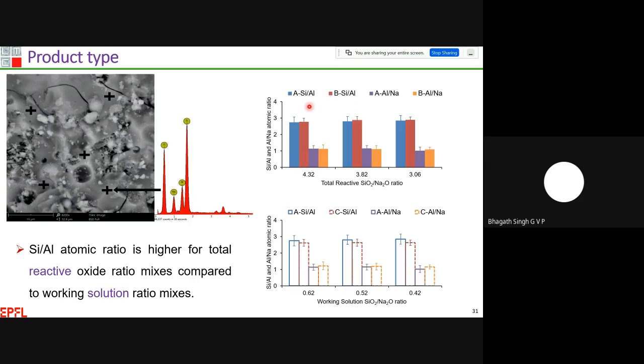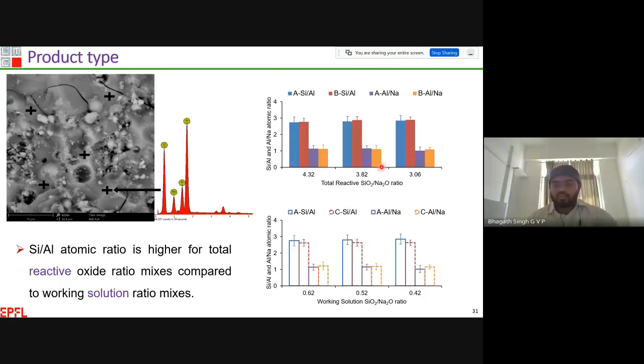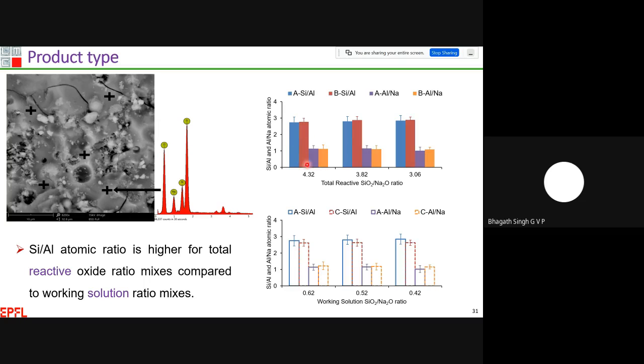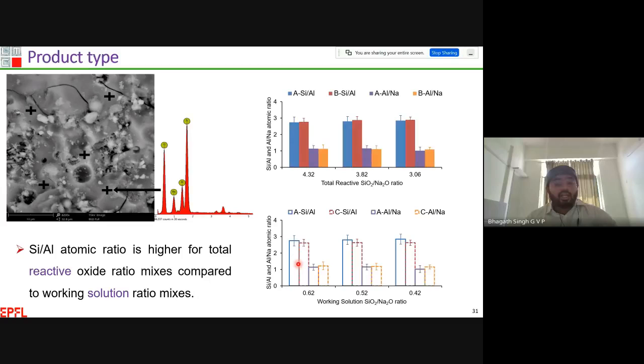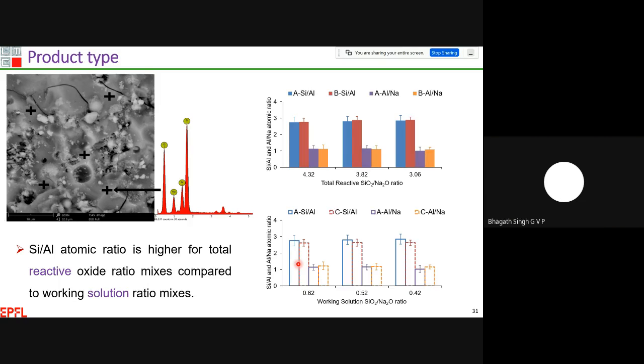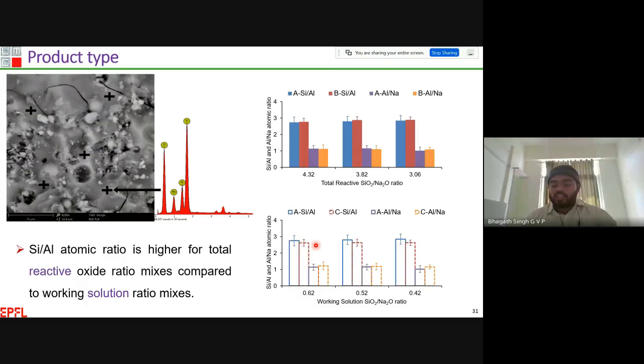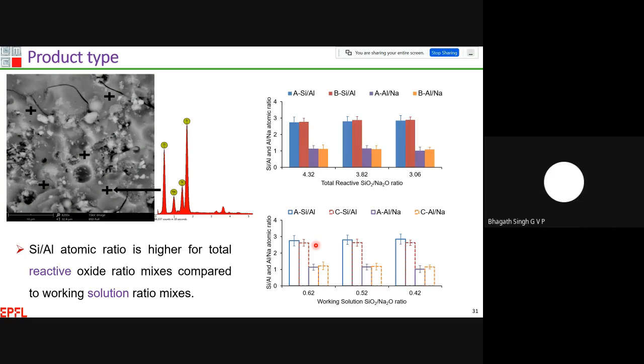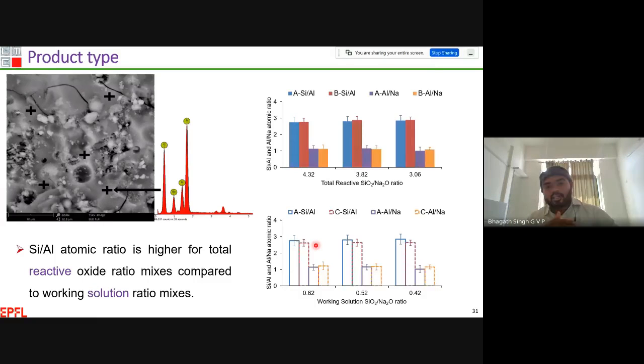Here I have determined the silica to alumina as well as alumina to sodium ratios in various mixes: these are for the total reactive silica to sodium ratio, and these are for the working solution silica to sodium ratio. If you compare both, the silica to alumina ratios are quite high in the case of total reactive silica to sodium ratio, whereas working solution ratios show a lower silica to alumina atomic ratio. That is the reason we achieve lower compressive strength with the working solution ratios, because it requires some more silica in the system to reach a similar ultimate strength as the other fly ash source. We have to balance those ratios and quantities. Only then can we achieve similar products as well as similar ratios in the system. Thereby we can produce stable fly ash-based geopolymers irrespective of fly ash source.